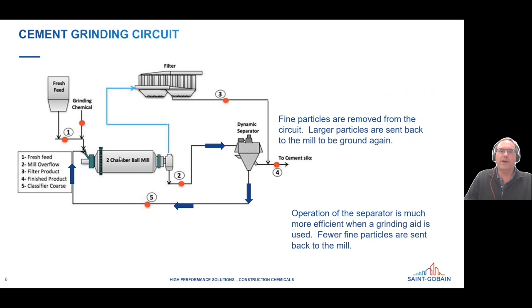So the material that passes out of the ball mill has a very wide range of particle sizes. So some of the particles are fine enough that they're ready to be taken away as cement, and other ones are actually still too coarse. So what happens is it goes through another piece of equipment called a separator. And the separator does exactly that. It takes away the fine particles and sends them out to the silo because they're done, but the heavier particles fall through the separator and they're actually carried back around to the beginning, to the start of the ball mill. So as the ball mill is running, what's going in is a combination of the fresh clinker and the returns that were too coarse to be ground the first time.